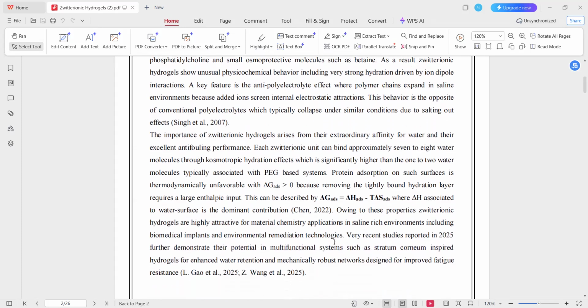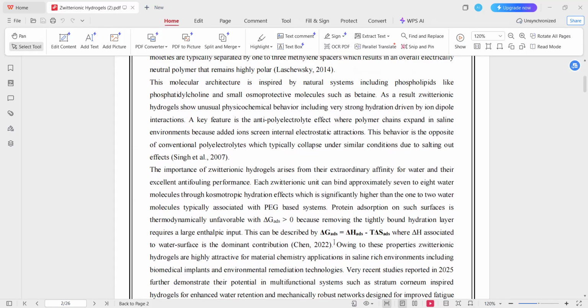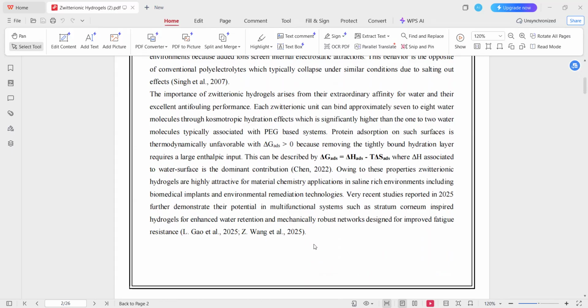This behavior can be explained by using the thermodynamic Gibbs free energy equation, which is delta G equals delta H minus T delta S. Here, delta G represents Gibbs free energy, delta H represents enthalpy change, T represents temperature, and delta S represents change in entropy. In Zwitterionic hydrogels, the hydration layer is very tightly bound, and when a protein or bacteria wants to adsorb on its surface, they first have to remove this hydration layer. But removing this layer requires a large amount of input energy. It means delta H becomes positive, due to which the value of Gibbs free energy also becomes positive. This positive value indicates that the reaction cannot proceed naturally or spontaneously. So protein adsorption becomes thermodynamically unfavorable. This is why proteins, cells, and bacteria do not stick to zwitterionic hydrogel surfaces easily.